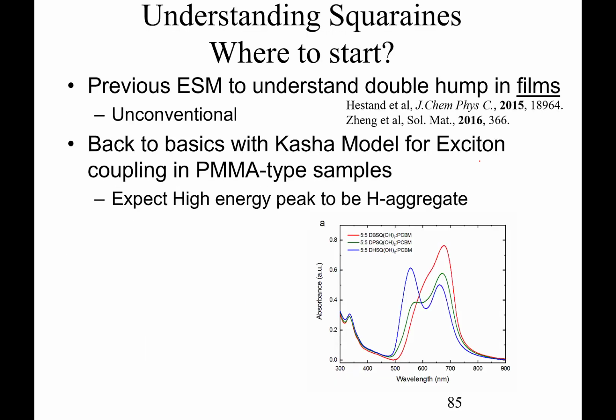Where do we start? We have used something called the essential states model to understand the double hump in films, and that was pioneered by Nick Hestand and Frank Spano with Chenyu Zhang and myself in this article from 2015. It's unconventional to use this essential states model, but it works really well for these polar materials, these quadrupolar materials actually. We also have thought about going back to basics with a typical exciton model, a Kasha model for exciton coupling in these polymethyl methacrylate type samples. Again, we think that this peak in here is going to be associated with the H aggregate.